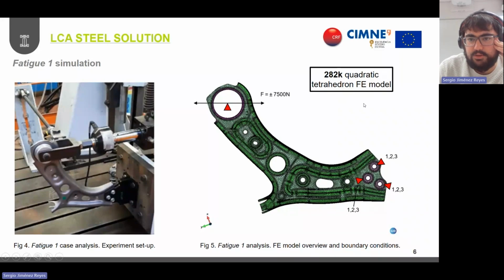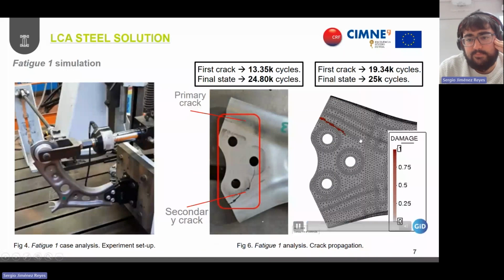This is the numerical model that we built using quadratic tetrahedron finite elements. And this is the type of result that we obtain in terms of crack propagation along the fatigue simulation. So these are the results that Michele more or less showed. I think that what Michele was showing for this crack was not the damage variable itself, but the fatigue reduction factor variable. And what you can see here is indeed the progression of the crack in terms of damage. So as Michele mentioned, we can capture both the first crack and the second one for this case study here.